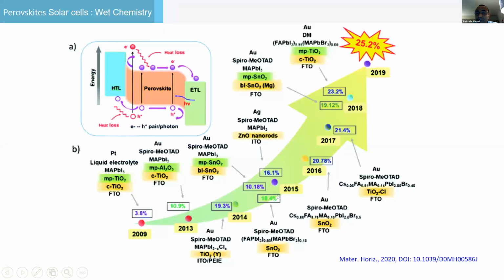With the help of compositional engineering, new materials, new ETM, and new device architectures, the efficiency has risen from 10% to 16% and 25.2% this year, with the new composition of 95. Compositional engineering has helped a lot, because this way you can modulate the absorption onset. If you modulate the absorption onset, you modulate the current, because the higher the absorption, the higher the current. And this FA95 and MAPbBr3 5% is the best one, giving 25.2% efficiency.